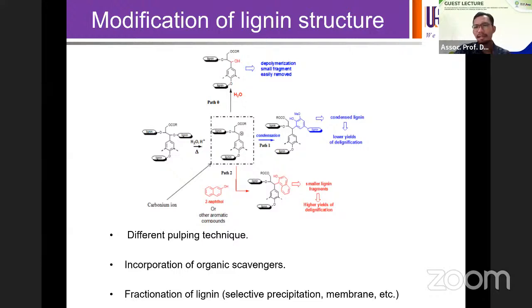This technique I actually learned during my PhD time in France, where we incorporate scavengers or chemicals during the pulping process. And when it forms the intermediate carbonium ion, it will interact or graft with the organic scavenger, forming smaller fragments of lignin. Smaller fragments of lignin can ensure us a higher yield of lignin, rather than if there were no scavenger, where it would combine by itself and form a more condensed structure.